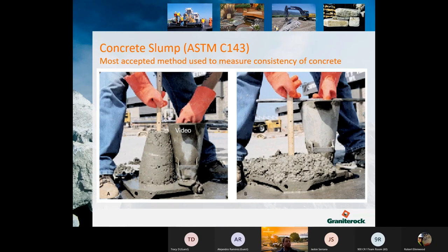You use a cone, fill it up 3 times, rodding 25 times each layer. Once the concrete is in there, you pull the cone off and the concrete will basically fall away, and you measure from the top of where it was to where the concrete lies now, and that's your slump. On the left side, we have a low slump around a 1 or 2, and on the right, maybe an 8-inch slump. So if you need a stiff mix, it has a lower slump. If you need something that flows well, it's a higher slump.